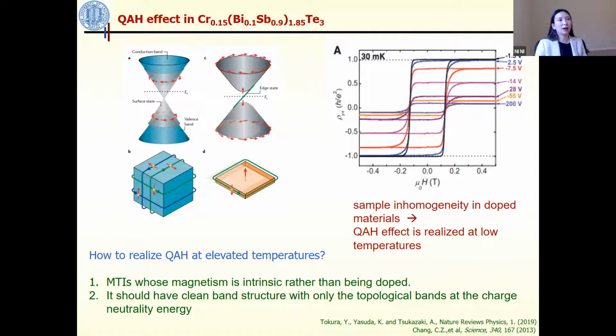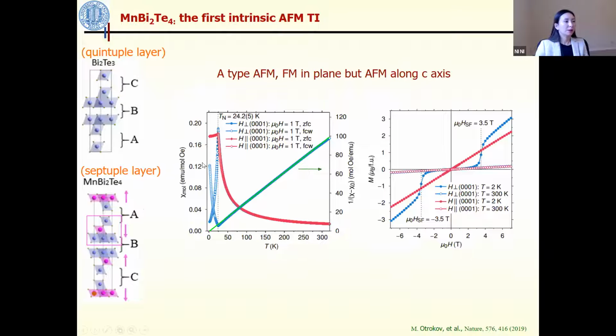The other way to think about it is, rather than improving the old material, we just look for new materials. What type of new materials? The new magnetic topological insulators whose magnetism is intrinsic rather than being doped. However, making such a material realization was very challenging. So finally, later, back in 2018, like 5 years later, manganese bismuth 2 tellurium 4 was discovered as the first